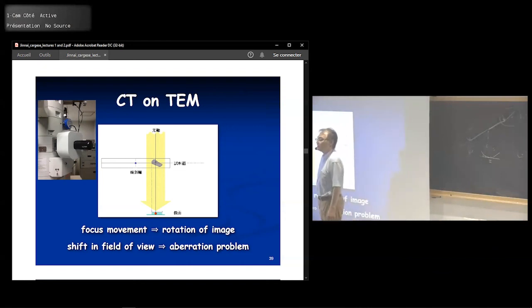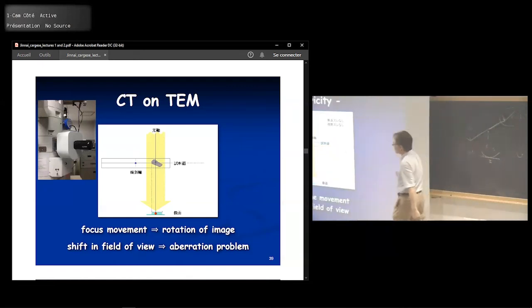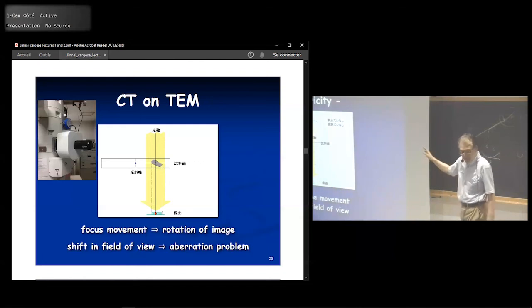Like this. This is your holder, and then your sample is on the holder, and then you stick the whole thing into the instrument, and then you tilt like this. And then this is a picture you are taking a look from this side. So what you need is that you need to move the sample holder so that your sample is on the tilt axis. That's what you need to do. Then your sample rotates along the tilt axis. So it's a very important thing when you do electron tomography.